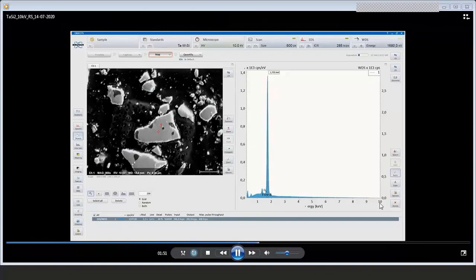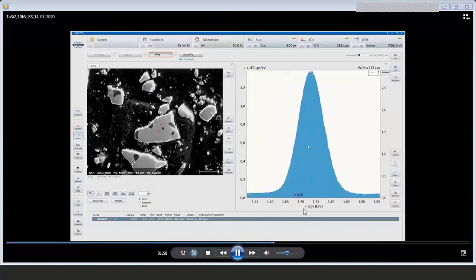It's acquired with 10 kilovolts. And we then zoom into the area of interest here, of the overlap of the different lines. And you see here the range scan acquired by WDS. WDS is, as you know, energy selective. So one energy after the other is acquired. So in order to acquire a spectrum or a section from a spectrum, we have to change the inclination of the analyzer crystal. So the theta angle is changed. And what we see here is recording now of an energy range scan. We see a first peak, and we can use the finder function to identify what peaks we find here.